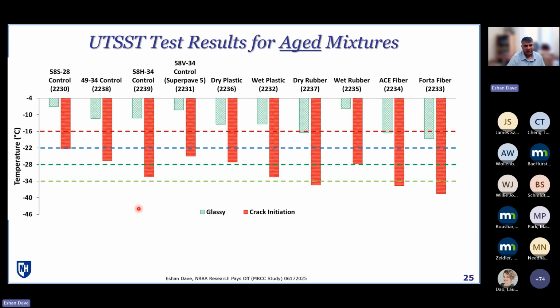The uniaxial thermal stress strain test. What I'm showing here is really two temperatures. One temperature tells you when your material starts to behave more glassy, where it's starting to lose its capability to easily strain and also recover back from applied stresses. And the second is when it's typically expected to crack, at what temperatures, assuming the cooling rate that this test uses, and so on.